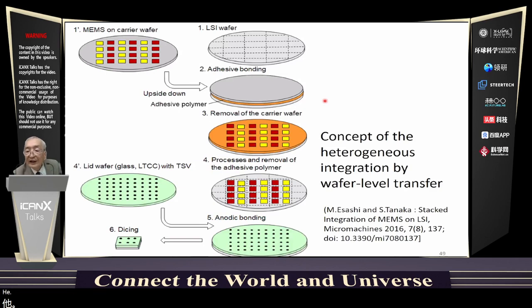The heterogeneous integration of MEMS on LSI is enabled by wafer level transfer shown in this slide. MEMS are fabricated on a carrier wafer to avoid damaging the LSI, and hence various MEMS, for example, PZT film formed at high temperature, can be applied. The MEMS wafer is bonded to the LSI wafer with adhesive resin or by bumps in two. The carrier wafer is removed, leaving the MEMS on the LSI wafer as you can see in three.